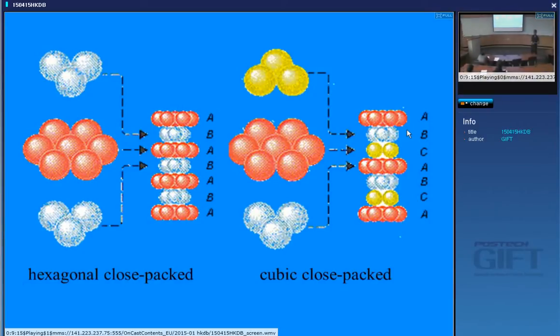In pure iron, you only find the hexagonal form deep inside the earth where there's a lot of pressure. Now, if pressure favors a phase, that means it must be a higher density, sorry. So hexagonal close-packed iron has a higher density than austenite.